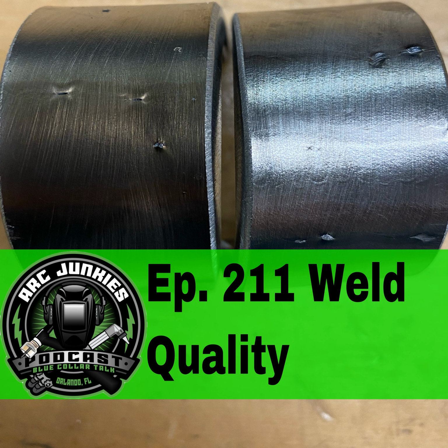Now, this can be the same thing for your root. I can't have any more than an 1/8 inch weld reinforcement on the back side of the plate or on the inside of the pipe, according to D1.1. I can't have any more than an 1/8 inch. Anything more than that, that's an automatic defect, and we want to try to avoid that. So just watch your travel speed as you're going through the material.